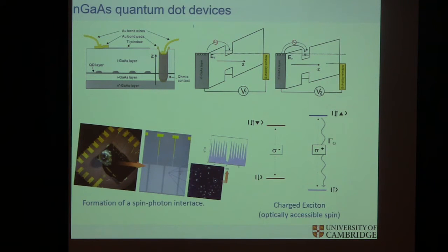If you find the wrong sample, count rates drop down to 10K, and the line width is a couple of gigahertz. So it depends on how good quality the wafer is, the original gallium arsenide wafer. But it is possible to have reasonably clean systems. All right? So that's why, coming back to that, it justifies that for us, for the experiments where we need strong counts, 8 million photons coming out, I'm happy with that.